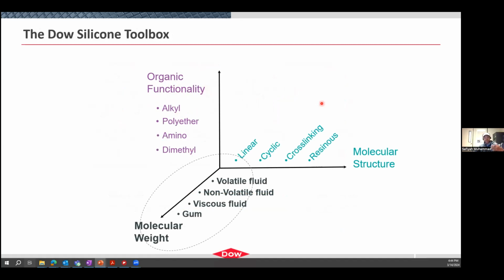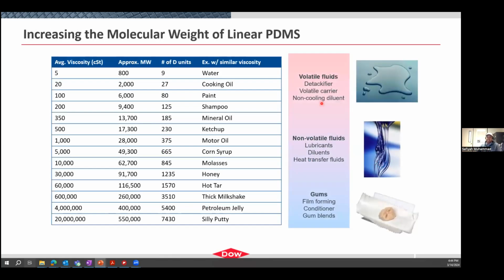So if we think about polymers, polymers will always have a molecular weight distribution. And so we can actually take advantage of that in order to get certain properties. So if we think about PDMS, again, PDMS is a chain of D units capped by M units, or just D units capped with OH groups. We can change the number of D units in order to change the overall molecular weight. And as you increase the molecular weight, you actually increase the viscosity, so that you can get a list of materials that range from a viscosity of water all the way up to something that is like silly putty.